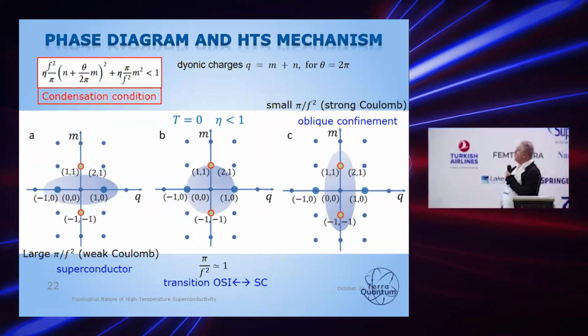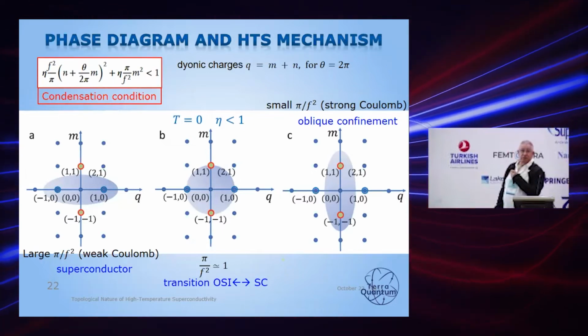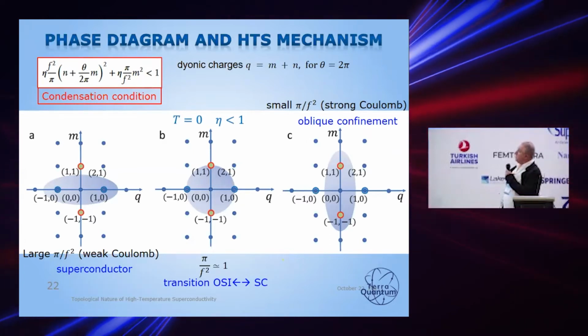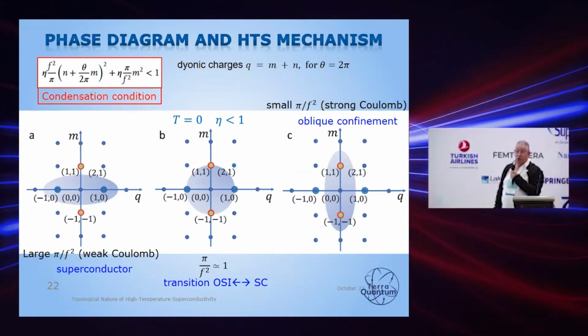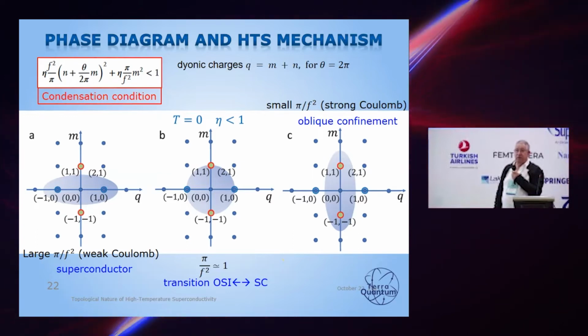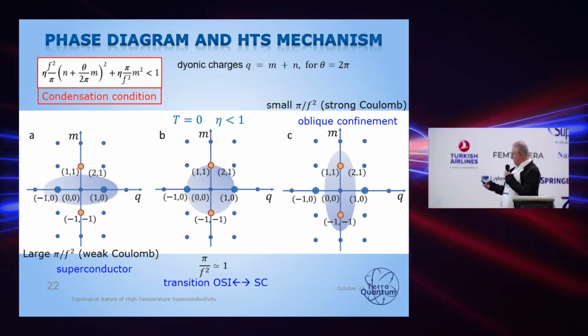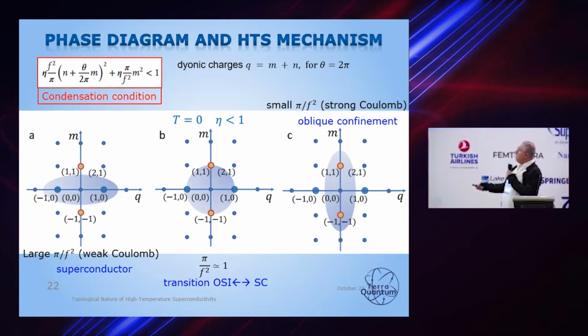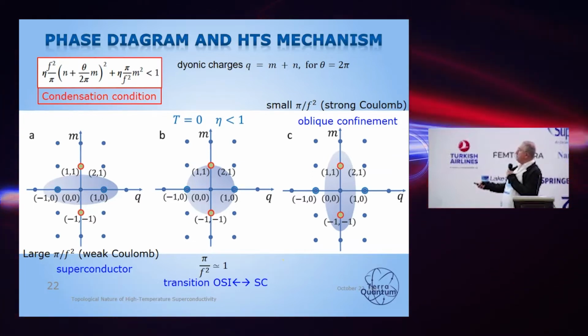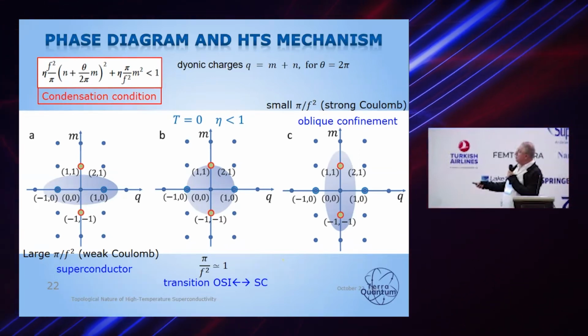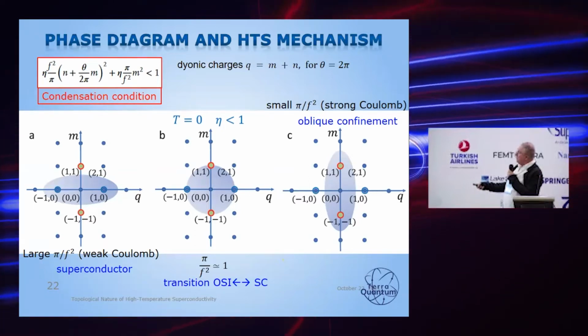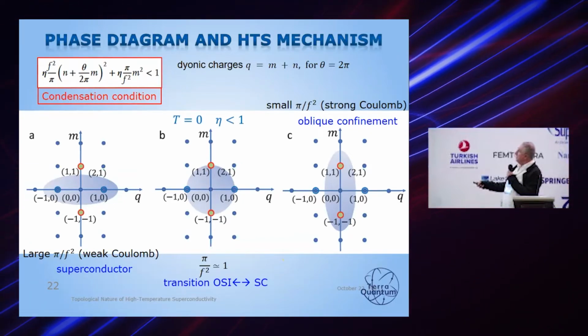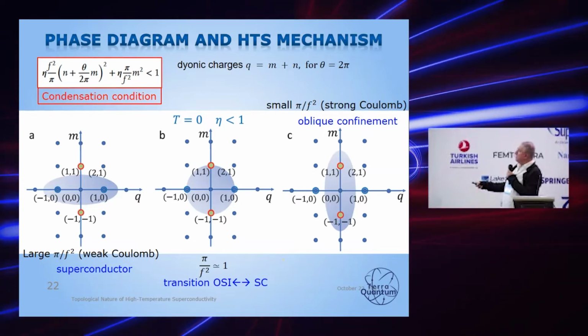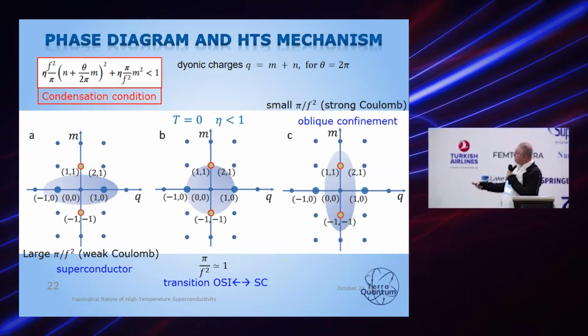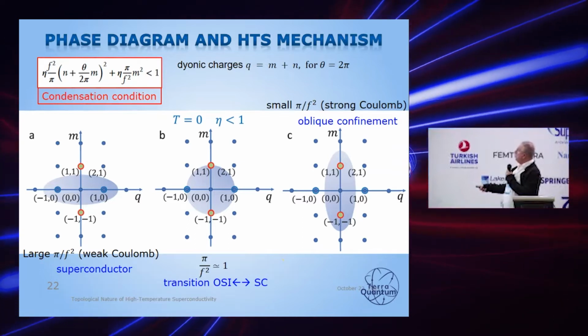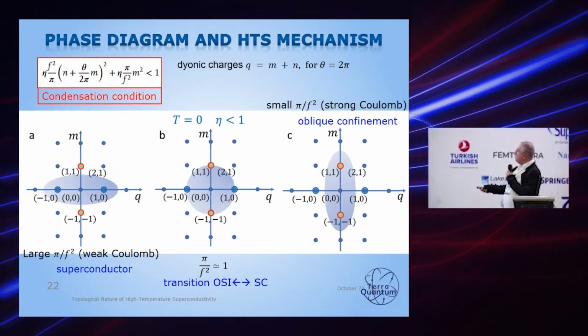So this is where we have the full description of phase transitions which occur in this high temperature superconducting state. Depending on the strength of our Coulomb interaction, which we can vary, for example, by changing either the temperature or the doping, we can have either a superconducting state where these Cooper pairs make a condensate, or we can have a transition between the states. And we can notice that when we have this transition, which includes coexistence of dyon condensate and Cooper pair condensate, our parameter eta is less than 1, and it means that this is a direct transition not involving any intermediate phase, exactly as we see in the experiment. Or we can have oblique confinement, and this means that we have this oblique superinsulator, which is a pseudogap state.